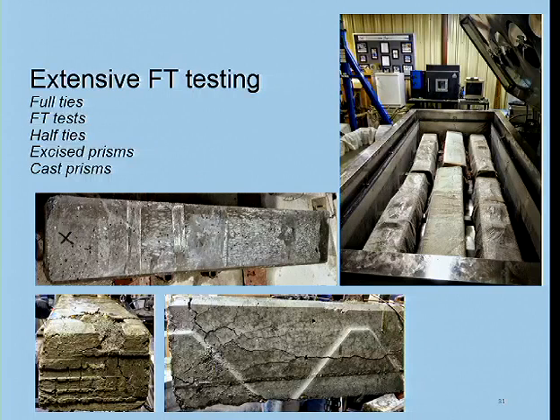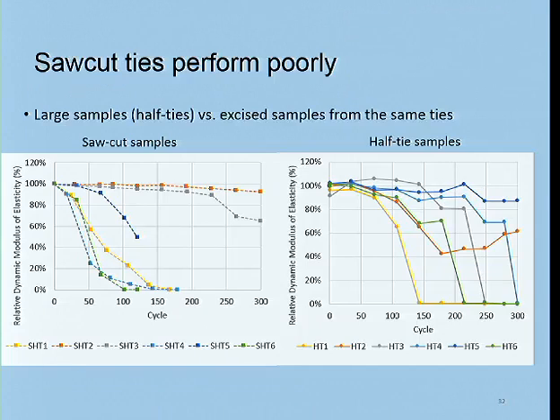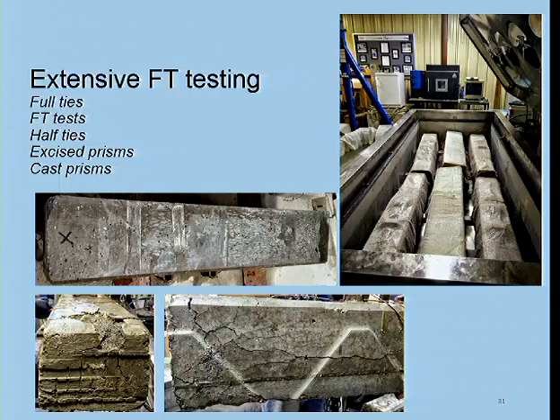So there was an extensive freeze-thaw testing program in this project. You see here, we tested full-length ties inside the specially manufactured freeze-thaw chamber at Kansas State. And you could see that we could achieve the kind of distress that we would expect with freeze-thaw damage. But I should say, we tested lots of different configurations: full ties, half ties, prisms that were cut from the samples, from ties, and also prisms that were cast with no steel in them.